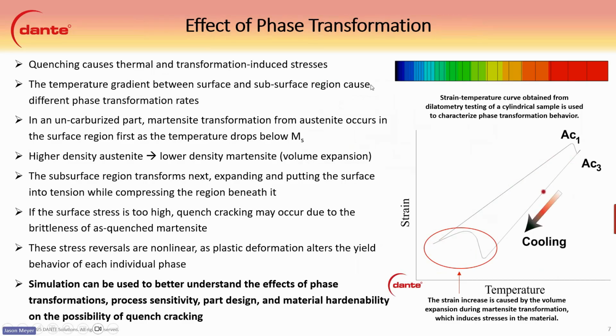So the effect of phase transformation. Quenching causes thermal and transformation-induced stresses. Basically, at the basic level here, the temperature gradient between the surface and the subsurface region causes different phase transformation rates as well. So there's a temperature gradient that causes a phase transformation gradient. And up here, I have a little example of a one element deep finite element model, where this would be the surface. You can see the blue color represents a cooler part, and then the red color represents the hotter core of the part.